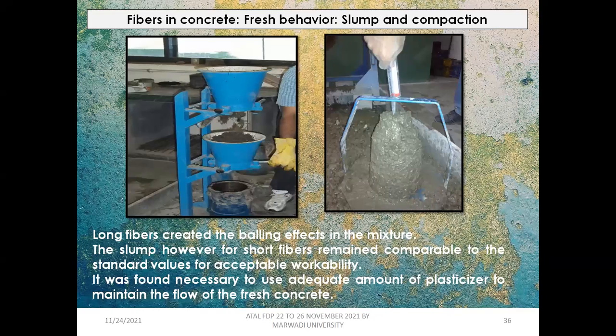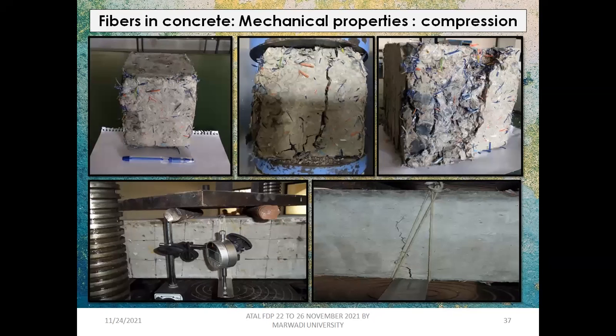Then these are some of the images. I'm not going to read each and every line here, but I wanted to show you that it's quite possible to work with these fibers, and long fibers created a balling effect. So we should not use those fibers where workability is of prime importance, for example where dense reinforcement is placed. We should avoid using these in such applications. Similarly, you can see some of the images with the addition in the concrete, and the results of the compressive tests, the toughness test, and the flexure.